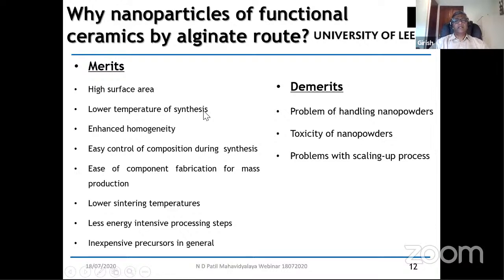It has the lower temperature of synthesis, and therefore restricts, or is one of the reasons to restrict, grain growth. It always produces with enhanced homogeneity, so you don't need further purification to increase the homogeneity or purity of the material. So as it is, once you calcine, you get consistently high purity material. Easy to control composition during the synthesis process. The ease of component fabrication for mass production. So it is easy because it's scalable. This particular method is scalable.